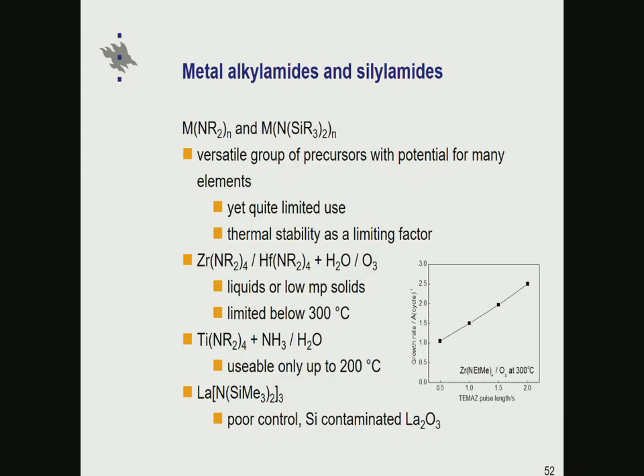Still a couple of homoleptic groups in general. The next one is where we have a nitrogen donor, so they are either alkyl amides or silyl amides. In both cases there are metal-nitrogen bonds. And again, quite versatile groups, lots of possibilities for various kinds of metals, but still reasonably limited use. The problem in quite many cases has been the limited thermal stability, compared to those compounds where oxygen is the donor bonding with the metal. So these are not as stable, at least in most cases.